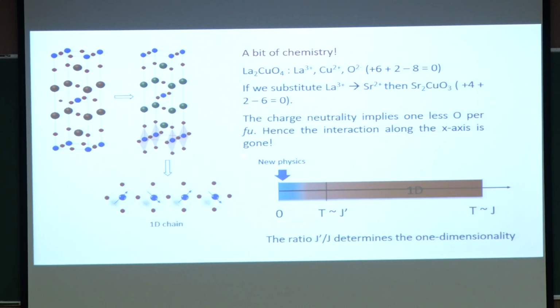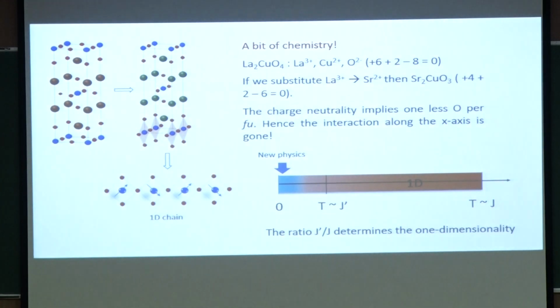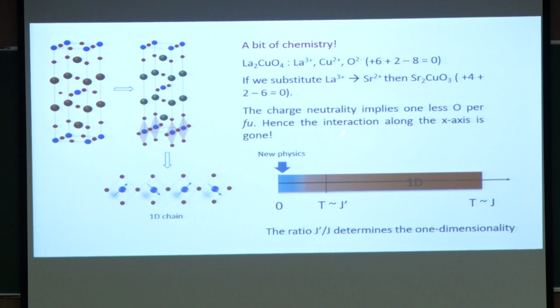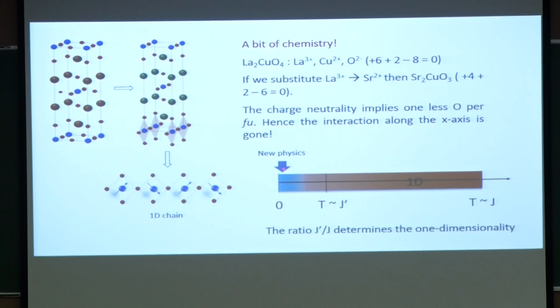You see that? So, depending on the ratio J prime by J, because in real systems there is no ideal one dimensional system, there is always a non-zero J prime. The question is, how small is this ratio J prime by J? And in the case of strontium 2 copper oxygen 3, it so turned out that this ratio J prime by J is of the order of 10 to the power minus 3 or minus 4. So, 3-4 orders of magnitude difference between the two J's. Therefore, this compound is a very good representative of 1D systems. Is this clear? Up to now everything is fine? All right. So, if you want to study the physics of one-dimensional chains, then you have to find systems which are in this region of this one-dimensional phase diagram that I have drawn here.